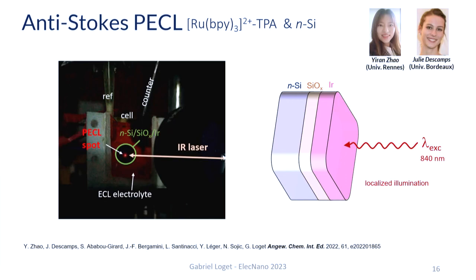So here you can see a photo of our setup. We have the different elements. This red thing is the ECL electrolyte here. The green discs represent the active surface of our anode. The IR laser, which is invisible, and this is 840 nanometer, comes from the right to the left. And the tiny red spot we see here is the PECL process. So here we have red illumination due to this upconversion process.